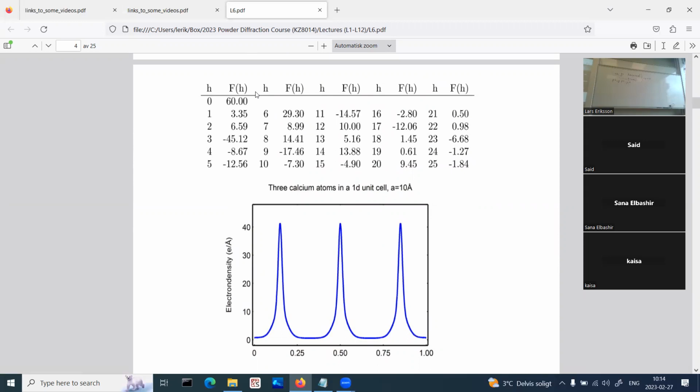The requirement that we only have positive and negative structure factors shows that we have a centrosymmetric structure model. So if we invert it, we will get exactly back. If it's not centrosymmetric, then unfortunately the structure factors will be complex, all of them in general. But still, we can't detect the minus sign.